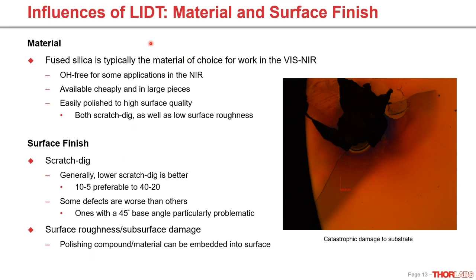Typically, fused silica is the material of choice for a lot of the work in the visible and the near infrared. Hydroxyl-free is available for some applications because that does have some absorption bands in the near IR and telecom region. Fused silica has the advantage of being available relatively cheaply and in relatively large pieces, and it's easily polished to a high surface quality, both in terms of surface finish that is good scratch dig, as well as low surface roughness, both of which can contribute. So we're going to look at that here. Typically, you want a lower number for scratch dig. 10-5 is preferable to 40-20. 40-20 is better than 60-40, et cetera, et cetera.